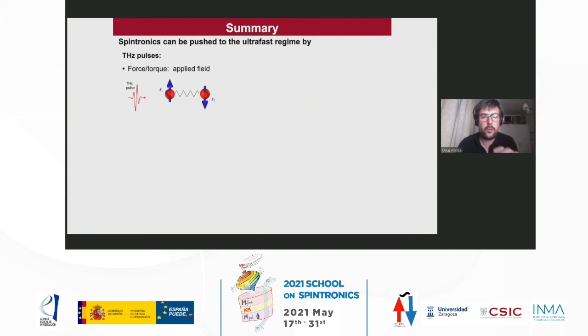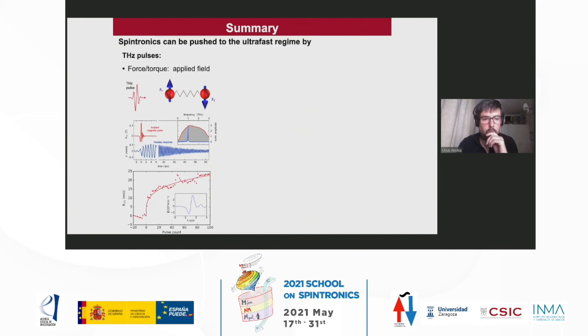I have shown you two examples: first, inducing magnetization precession in nickel oxide using the magnetic field of a terahertz pulse, and second, switching of an antiferromagnet using the electric field of this terahertz pulse.